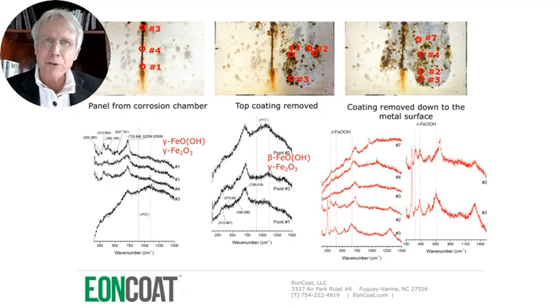10 years after Balasubramanian, in a lab in Wilson, North Carolina, my scientists tested that rusted panel I've been telling you about by removing the ceramic and using sophisticated tools to examine the spots which had healed. What they found was Misawite. The failure mechanism of EonCoat is the creation of Misawite. Once you get the amorphous form of FeOOH, the game is over. The layer will not flake off as crystalline FeOOH does, and it cannot corrode further because FeOOH is the lowest energy state of iron.